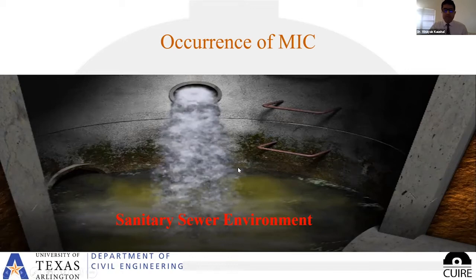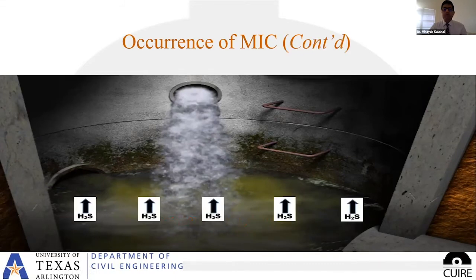reducing bacteria. You can see here. So these bacteria basically colonize in the slime layer beneath the surface of the flow, and create hydrogen sulfide as a byproduct as they begin to break down the organic matter. So now the hydrogen sulfide gas is generated when first the dissolved hydrogen sulfide is stripped from these flows.